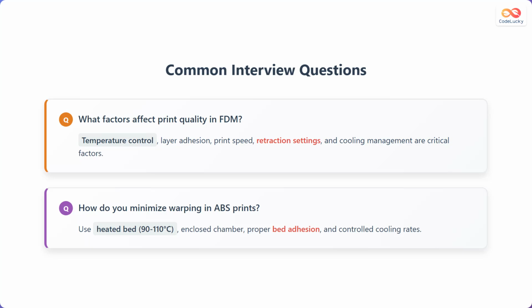Second, how do you minimize warping in ABS prints? The solution involves using a heated bed at 90 to 110 degrees Celsius, maintaining an enclosed chamber to control ambient temperature, ensuring proper bed adhesion through techniques like using an ABS slurry or specialized bed surfaces, and implementing controlled cooling rates to reduce thermal stress during the printing process.